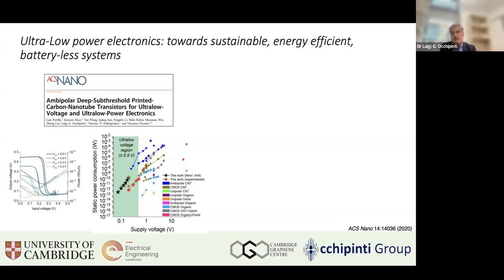We developed a unique printed semiconductor carbon nanotubes-based transistor technology with nanodielectric, and we use this approach to exploit sub-threshold regime operating devices. So instead of operating in the normal regime, we use the carbon nanotube-based transistor operated in the sub-threshold regime with operating voltage lower than 0.5 volt, achieving power consumption in the range of 10 femtowatts up to 1 picowatt per micron of channel width, which is just a fraction of the normal leakage current in conventional CMOS circuits. And at that time, it was the record low power consumption reported.